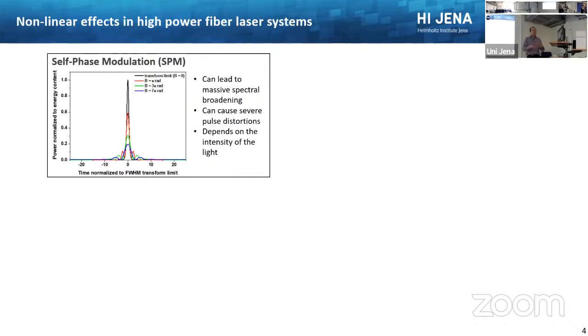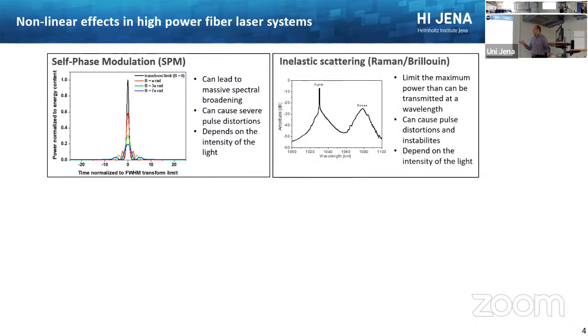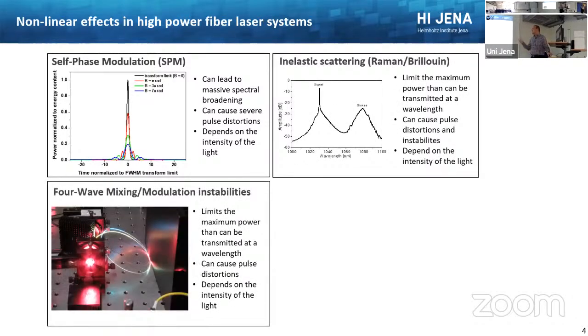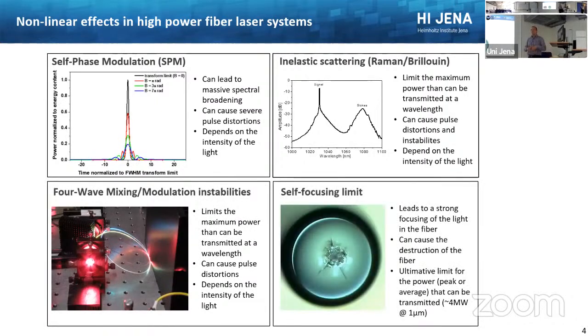So there are a huge number of nonlinear effects that can happen: self-phase modulation, Raman scattering, four-wave mixing, and at a certain point, there's even this self-focusing limit, which is not related to the intensity, but to the peak power. So even if you make your waveguide larger, this doesn't help you. At about 4 megawatts, you will see self-focusing and finally destruction of the fiber. While most of these effects are, in certain ways, very useful, if you just want to amplify ultra-short pulses, you normally try to avoid all these effects, of course.